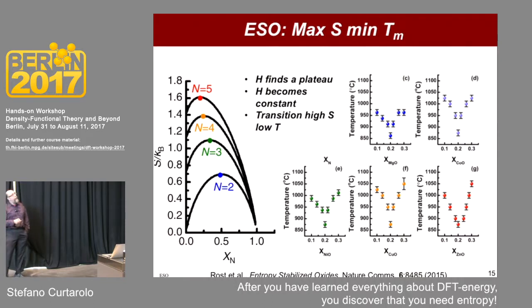And in fact, it's kind of a cross validation. If you take every one of these binary oxides and you change its composition from 20%, you see that you have a eutectoid in the 5-dimensional hyperspace phase space. It's phase diagrams, and the minimum transformation point is exactly at 20%, where you have 1/5. If it were symmetric, it would be exactly ideal entropy, which is actually, we are lucky, it's almost close.